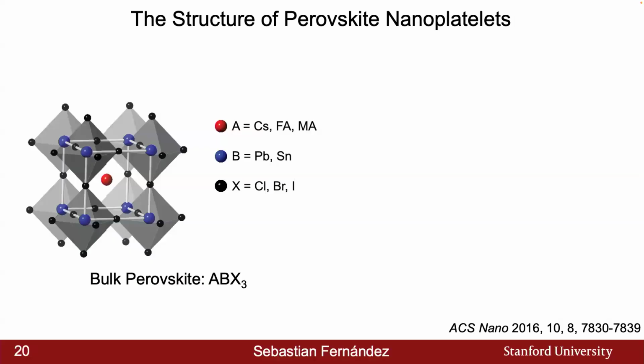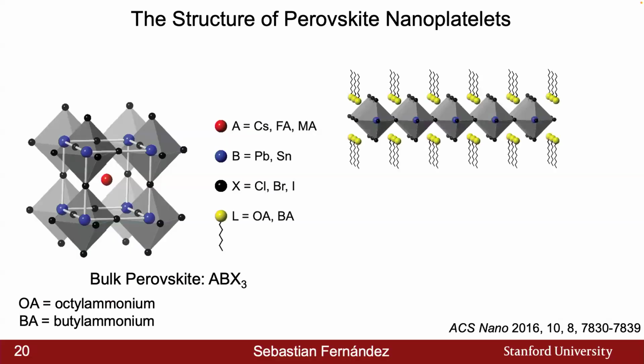So again, I'm showing the same ABX3 perovskite structure, only this time I'm briefly highlighting the unit cell, which will become more important very quickly. And we can start to introduce these ligand species, in which the authors use octylammonium and butylammonium here. When we introduce these to the synthesis of this material, we can confine the growth of the material to lead to something that looks like this.